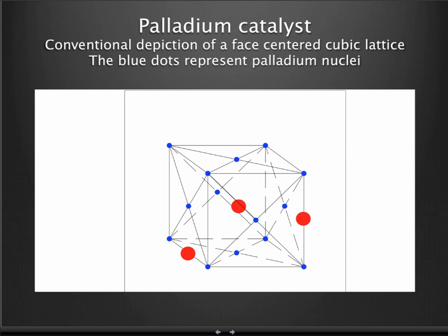The palladium can absorb approximately 900 times its volume of hydrogen at room temperature, which is equivalent to occupation of a bit over 70% of the octahedral chambers, assuming 1 monatomic hydrogen atom per chamber. Here the red spheres represent hydrogen, 1 in the center chamber and 2 at random locations in chambers shared with other cells. It should be noted that the cell represented here is not a discrete unit of the lattice, but is rather a division made for analytical purposes.